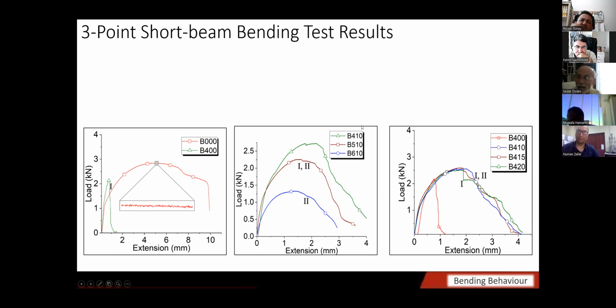Zafer, yes, maybe they may behave as stress concentration factors. Maybe they might have, but this is something which I believe. Maybe this is not the fact, but I believe that if we had done the same experiment only with the pre-sinter wires together, we might not have seen their influence very much. But even with the presence of iron boride phases, there is not much difference between the 10, 15, and 20%. There is only a difference because of the presence of iron boride phases, not because of the ratios of iron boride phases.